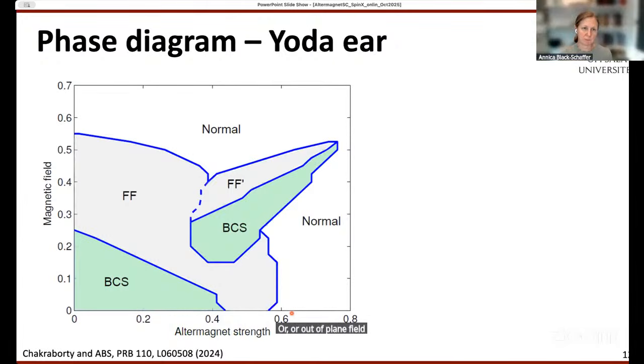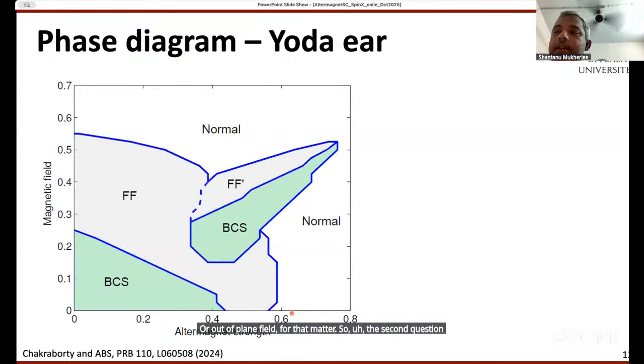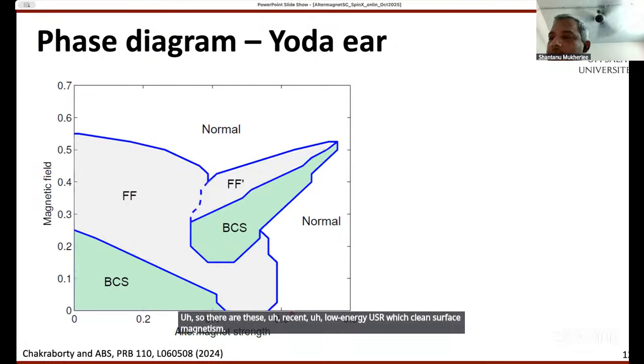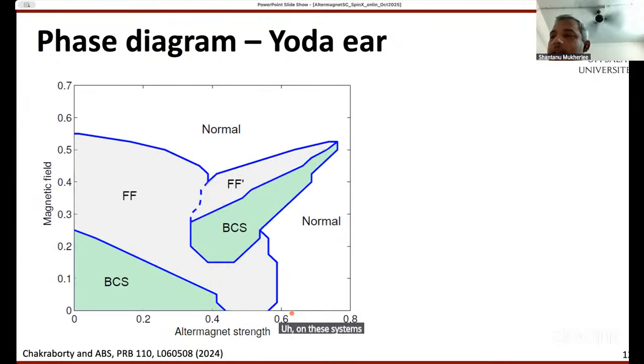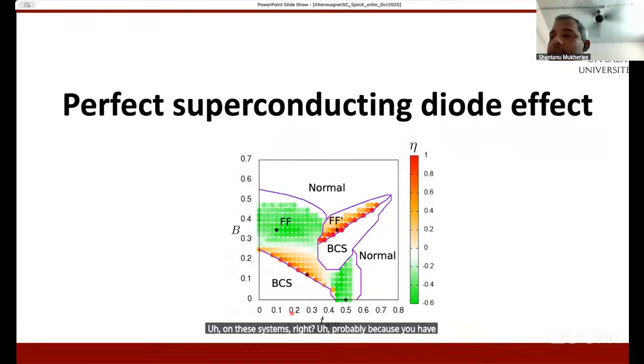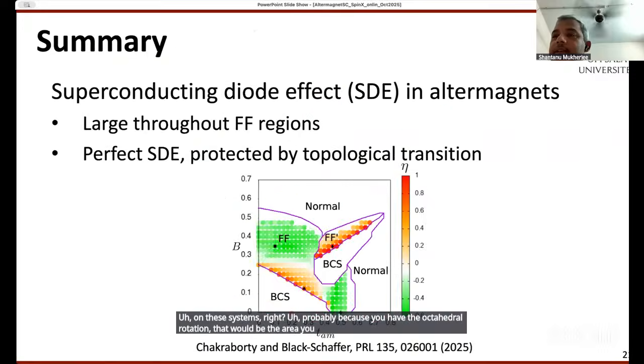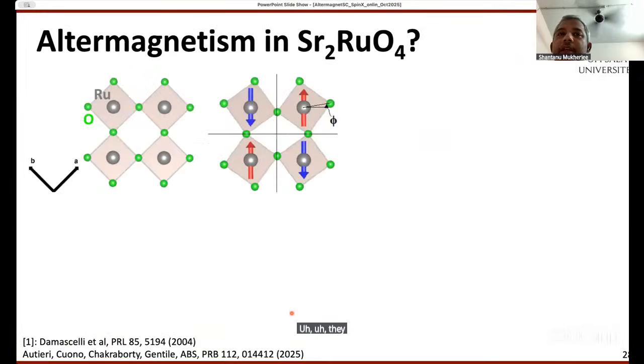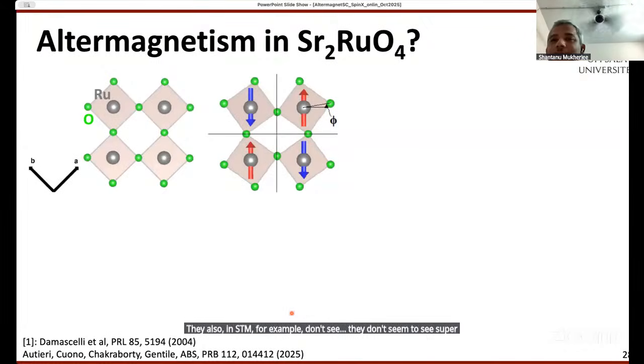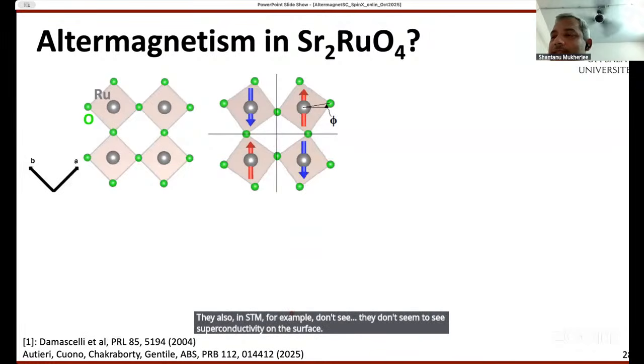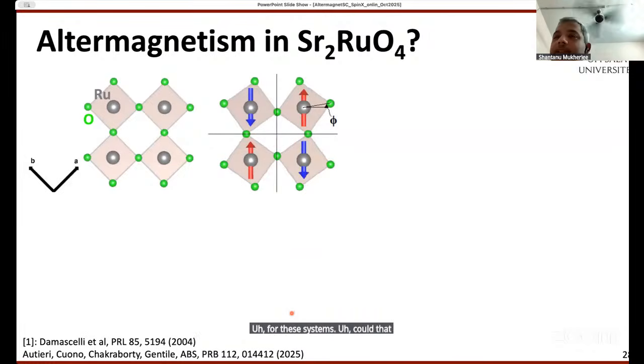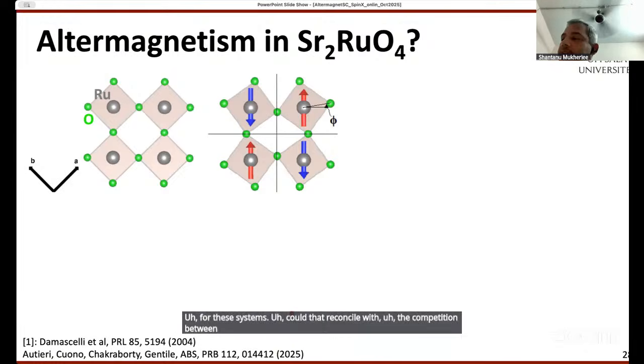Oh, okay. So the second question was regarding strontium ruthenate. There are these recent low energy muSR experiments which claim surface magnetism on these systems, right? Probably because you have the octahedral rotation, that would be the area you're looking at. They also, in STM, for example, don't seem to see superconductivity on the surface for these systems. Could that reconcile with the competition between superconductivity and maybe an altermagnetic model for strontium ruthenate?